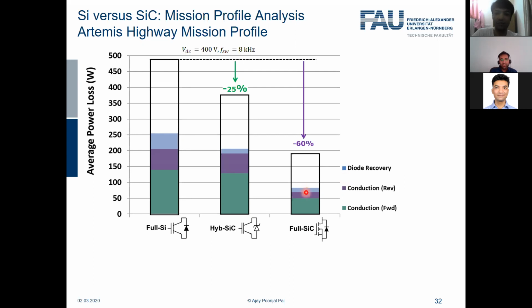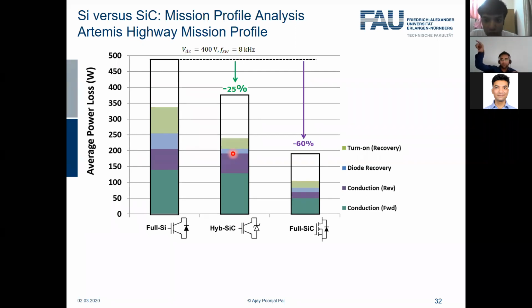So we also see that with the silicon carbide MOSFET, we can reach nearly the same behavior as with the silicon carbide diode, as far as the diode reverse recovery is concerned. And the next thing is, like I mentioned, when you change the diode, you don't save only on the diode, but you save also on the active switch, because the recovery peak is reflecting on the IGBT, the active switch. So therefore, we see a saving also on the active switch side. This green portion is due to turn on, the recovery part of the turn on waveform. And we see that also here there is a significant saving.